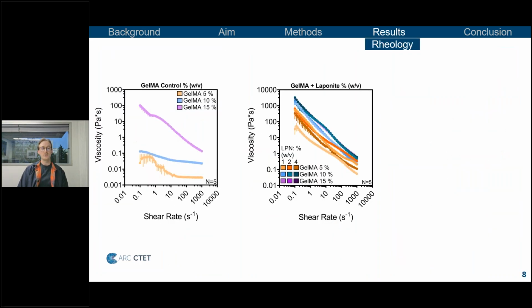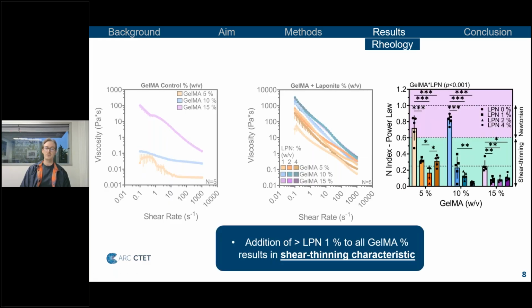So beginning with the rheology and the viscosity profile, we can see here the differences between the GelMA controls, where they lack viscosity and show a more Newtonian-like behavior, compared to the addition of laponite, which is these dark colors ranging from 1 to 4%. We not only see an increase in viscosity, but an increase in shear thinning characteristics, which can be further extrapolated looking at the power law regression model, at the n index, where something closer to 1 is more Newtonian-like, and something closer to 0 is more shear thinning.